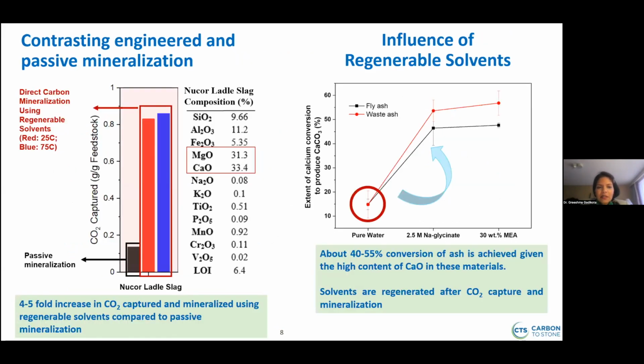So just to give you a sense of how this technology stacks up against passive mineralization. Passive mineralization is a technology where we just expose mine tailings or ground rock, and we expect that they will mineralize over time. They'll capture CO2 from air and they'll slowly mineralize. So here we have a really good example of Nucor Ladle Slag. Nucor Ladle Slag has just been sitting out for many months, and we noticed that over time it naturally captures CO2, and we're able to capture about 0.18 grams of the CO2 per gram of feedstock. But with our process, we're able to achieve a 4 to 5-fold increase in the CO2 that's actually captured.